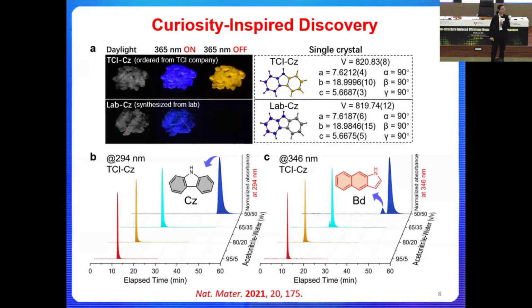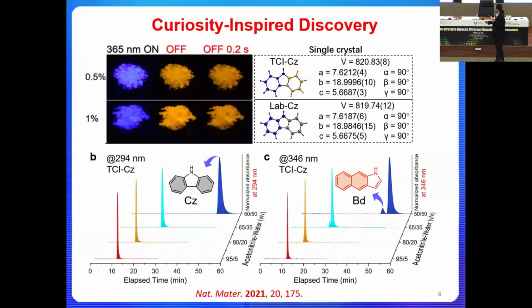All right, so it took us about 3 years' time to isolate this isomer from the carbazole, partially because they're isomers. And this molecule is also not very stable in solvents, in the presence of oxygen, etc. So we got them, we lost them, we got them, we lost them. It took us a long, long time. So we eventually found out that there is a small amount of the BD, which is the isomer, that coexists in the commercial carbazole. And when you add even 0.1% of BD into the original compound, you will be able to regenerate the phenomenon reported in the literature.